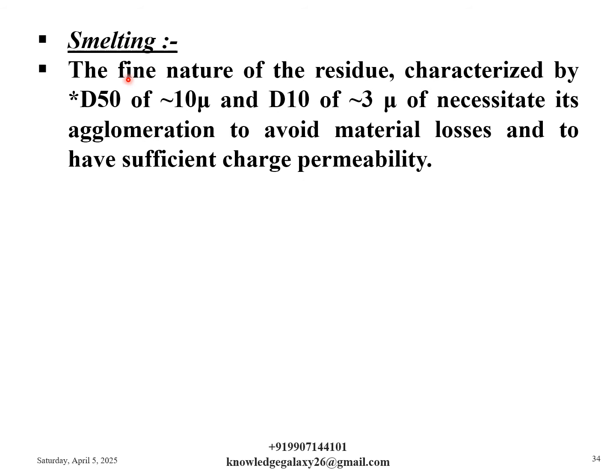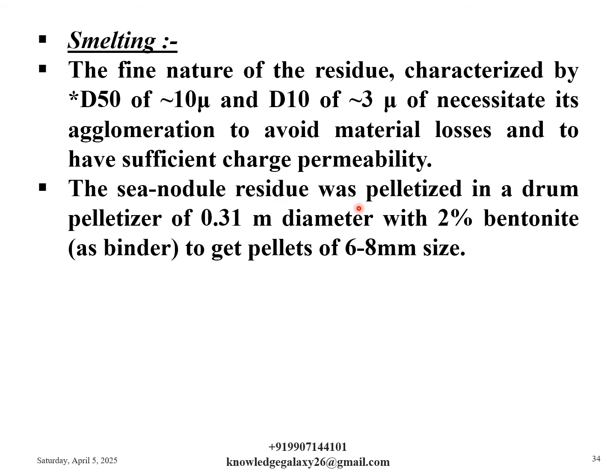So now let us discuss the smelting process. The fine nature of the residue, characterized by D50 equivalent to 10 micron and D10 equivalent to 3 micron, necessitated its agglomeration to avoid material losses and to have sufficient charge permeability. The sea-nodule residue was pelletized in a drum pelletizer of 0.31 meter diameter with 2% bentonite as binder to get pellets of 6 to 8 mm size.